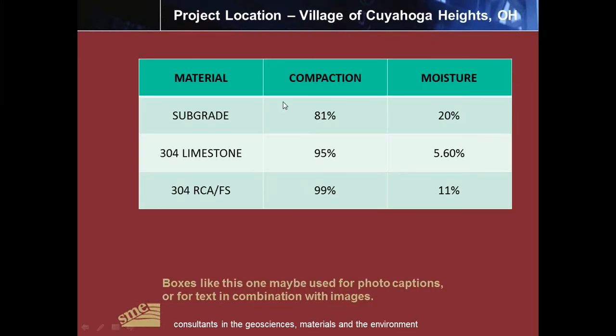The compaction results are as follows. The subgrade material, the cindery material, only achieved a compaction of 81%. You can see that the optimum moisture content was 18%, and so we were 2% over optimum, which makes this material a little more difficult to get greater densities. But like I mentioned earlier, the subgrade was stable under the proof rolling with the loaded tandem axle dump trucks.